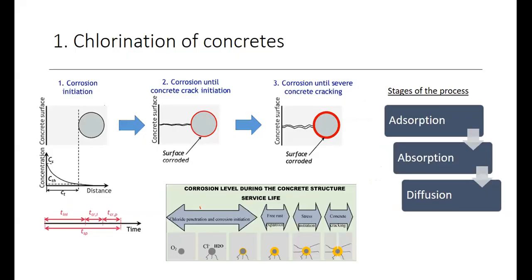Okay, so the first one is chlorination. As we discussed previously, chlorination starts with the chloride molecule coming to the surface of the concrete. Then it's like an adsorption. It will adsorb, and then with the moisture and the pore structures, it will absorb with capillary pressure into the concrete. After a certain level, it will diffuse, but we can't say whether it diffuses or finishes the absorption and gets to a stagnated level, which is the saturation level of the concentration. But this is the predictable way, the stages of the process.